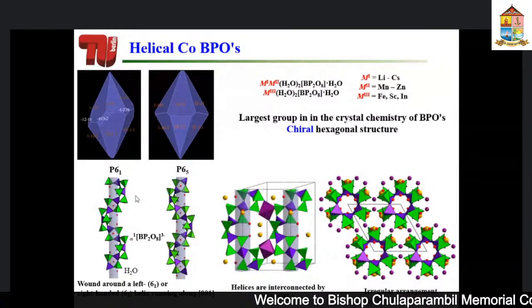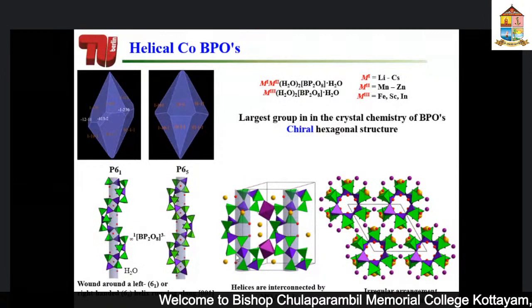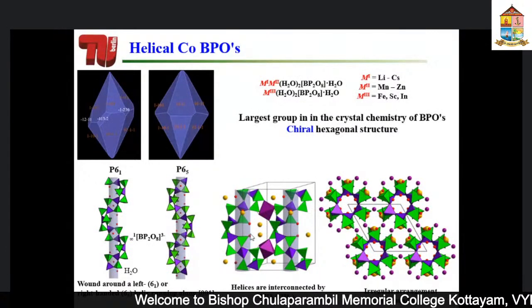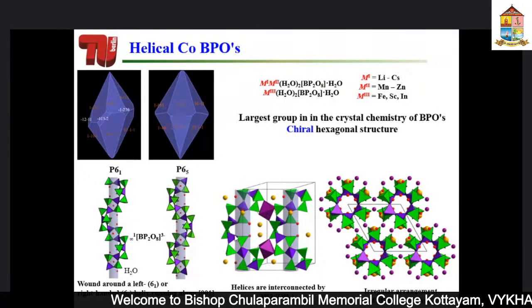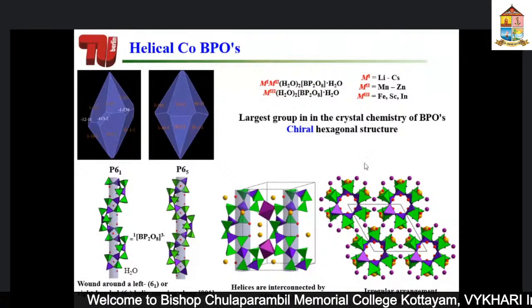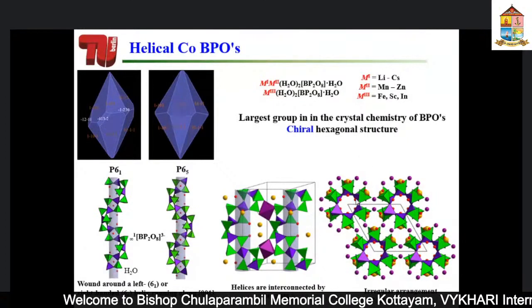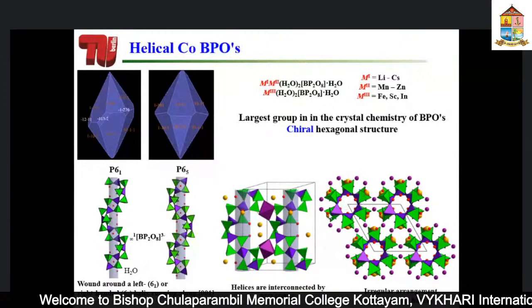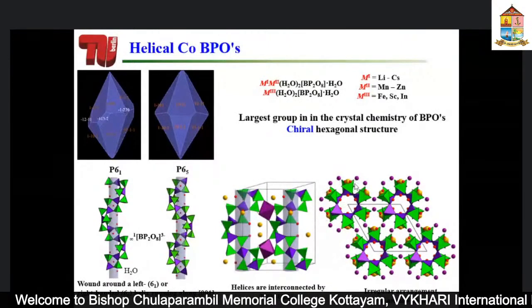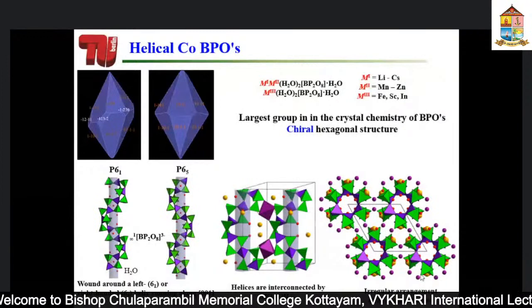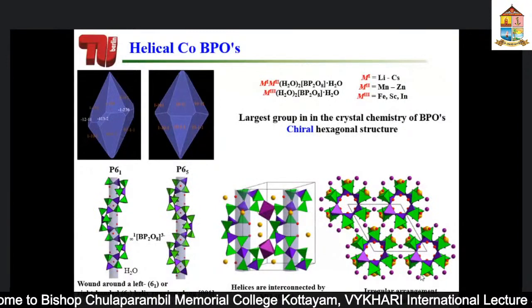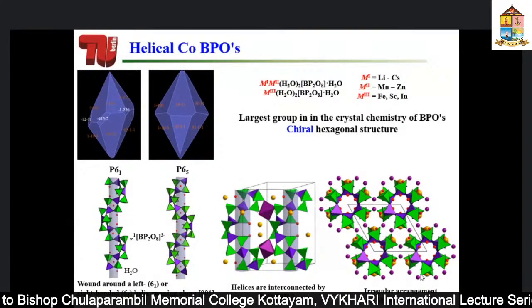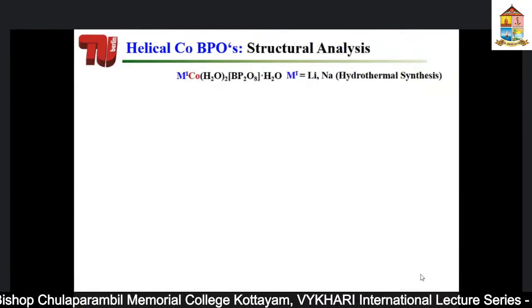So here you have the same architecture, let's say helical ribbons, and they're connected to your metal octahedra, and you also have some kind of alkali metals situated around the structure. As a whole, the structure looks like a dense rod structure. You could see these are the borophosphate chains, and these are the metals which are kept around. But nevertheless, we can make this kind of structure very easily via hydrothermal synthesis.